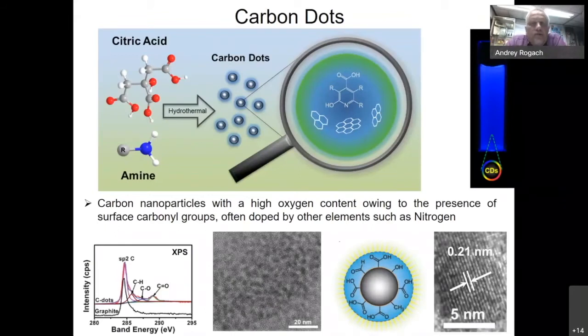So when we talk about these so-called carbon dots, these are small spherical nanoparticles. This is why we call them dots. They are very small. They're typically less than 10 nanometers in size, most of the time 2 to 5 nanometers in size. And these are carbon nanoparticles, definitely. That is why we call them carbon dots. And if we check the XPS spectra, we can realize they have high oxygen content because at the surface they have OH groups or COOH groups.